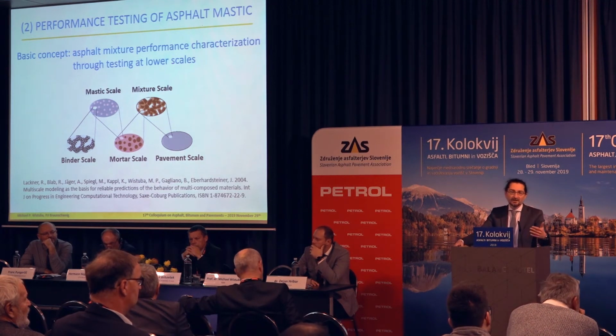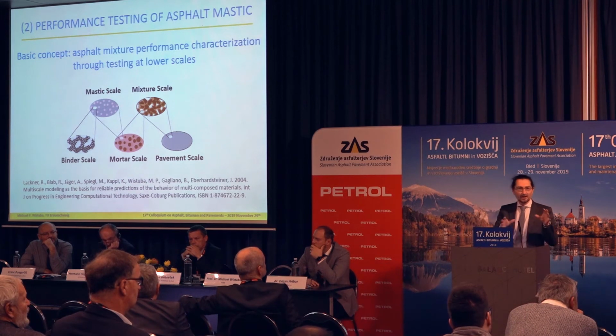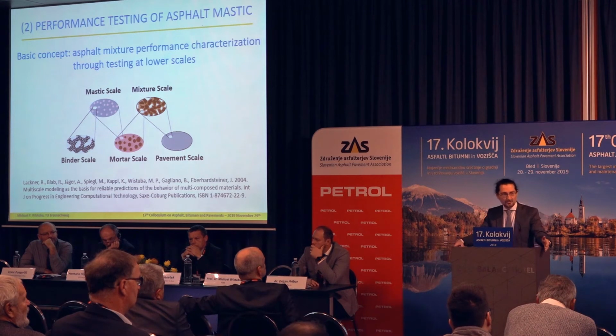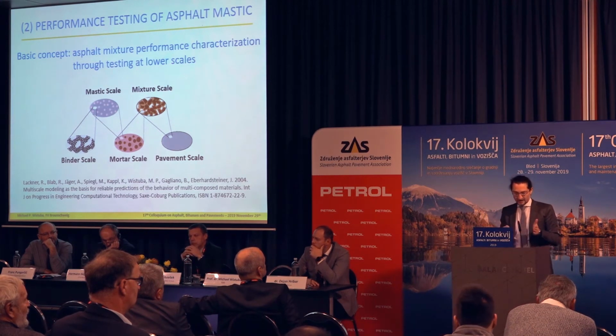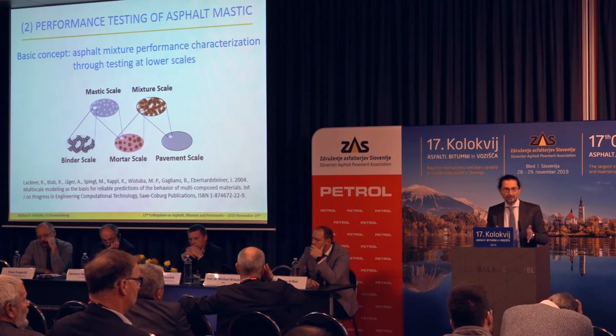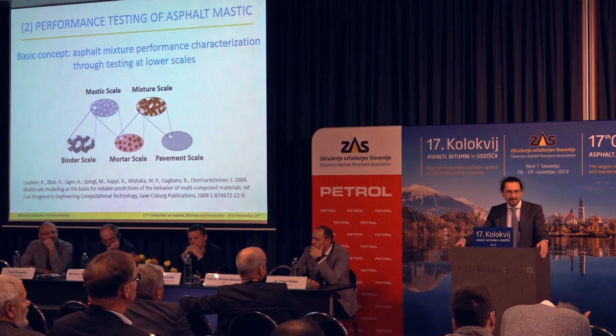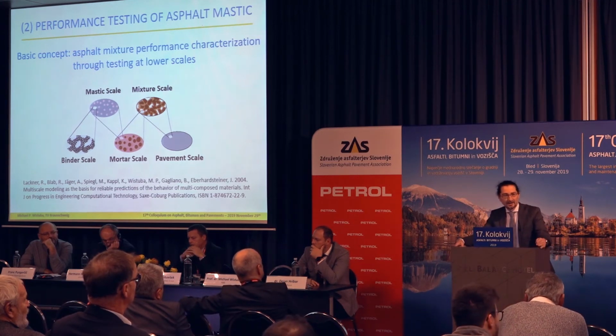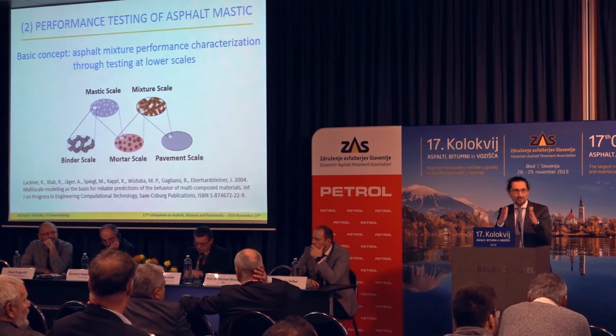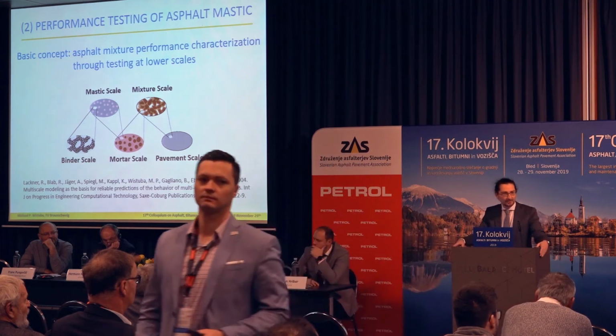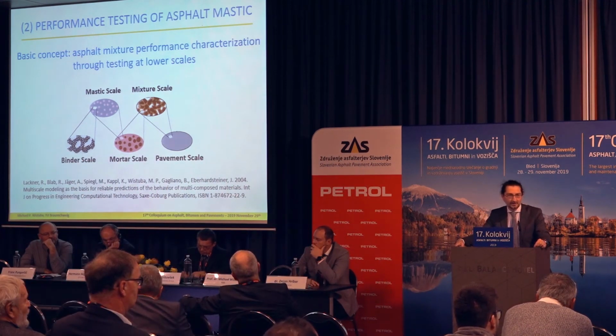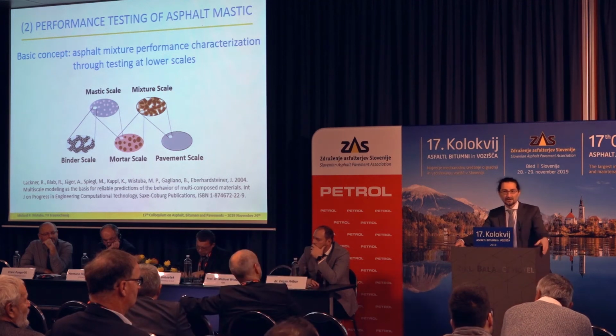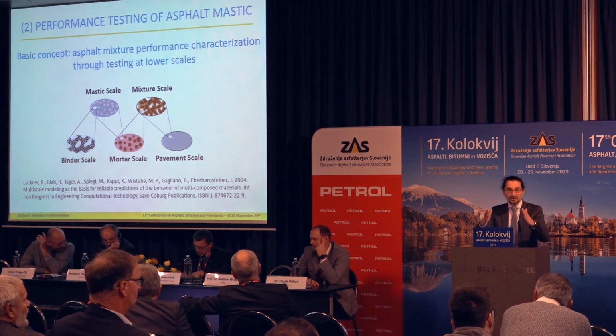Now you would say, how can I predict asphalt mix performance from binder testing? It's impossible because there is volumetric consideration, there is aggregate skeleton and so on. Of course you are right, but what is important is if we fix parameters of our asphalt materials, and we follow the concept which we have followed so far with standardized materials, where the grading is standardized, the binder content is standardized, and so on. Then we are already in a very narrow, sharp concept. And within this concept, it's possible to predict performance of such materials already at a lower scale. So we are not ignoring volumetric properties, but we are considering them because we are sticking to an empirical volumetric concept.